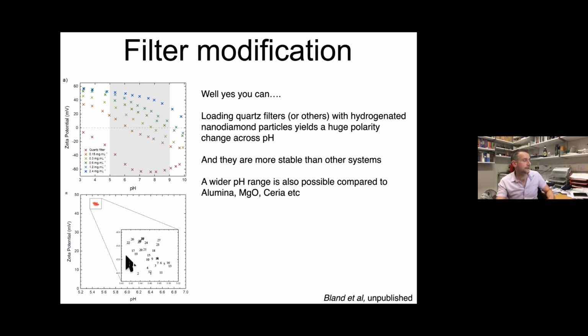This one here is the really exciting one for me. Henry here did the most boring experiment imaginable. We just keep pumping water through it and measuring the zeta potential over hours and hours. I don't know how long it took, I don't want to know. You can see here all the data points, and if you zoom in, this is the number of experiments he's performed, showing that the zeta potential is not changing. It's really stable. So this is super cool.